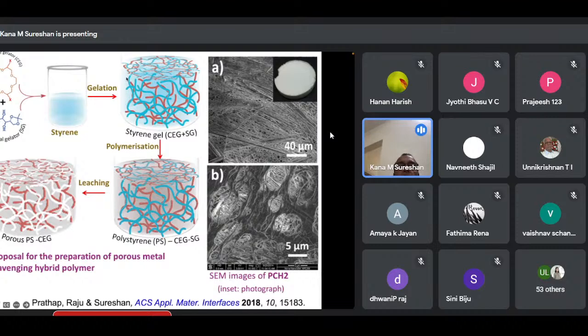You can remove this blue fibers by washing with water or other solvents. So that means you will have gaps or pores there. And inside you have crown ether. This is crown ether. The red one is crown ether. So your solvent can not only access the outside surface and also it can go inside and bind with potassium and remove potassium. So this is the real scanning electron microscopic image of this material.